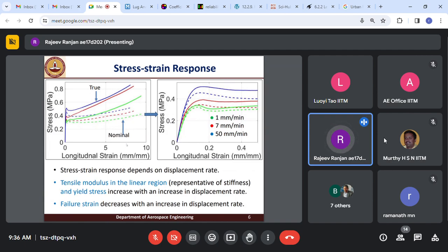Uniaxial tensile test was conducted at 1, 7 and 50 mm per minute. The dotted line here indicates the nominal stress, and the solid line indicates the true stress. For nominal stress, the initial cross-section area is used, whereas for true stress, the instantaneous cross-section area is required, and that instantaneous cross-section area we measured by measuring the instantaneous width and thickness of the specimen using DIC.